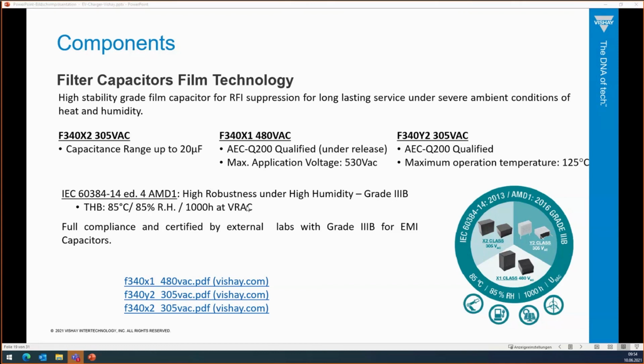And we apply the full AC voltage for 1,000 hours. After these 1,000 hours, the measurements show less than 5% tolerance of capacitance drift. This can be important for some customers, especially for filter capacitors, when you have high power as we see in the DC chargers. You have to have a proper filter behavior, otherwise you might get disturbances back into the grid or to your semiconductors that are even more stressed.